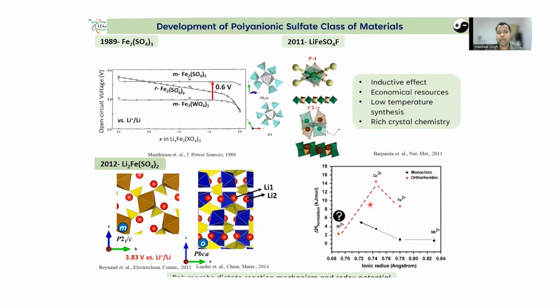Now, based on that, if you look at the polyanionic sulfate-based materials, they have a rich crystal chemistry and they are known for low temperature of synthesis. And because of that, we wanted to unveil newer cathode materials and see what the possibilities are. So if you look at the lithium metal bisulfate compound, there is a possibility of metastable phases for some analogs of the compound. For example, in the case of nickel, there's a possibility of monoclinic phases. Now, since these compounds were earlier made through energy-intensive routes such as ball milling, otherwise mechanochemical synthesis routes, these metastable phases were not stable, and therefore there was a need to find some new synthesis approach.